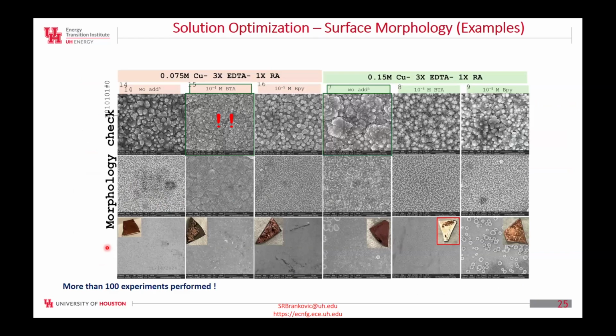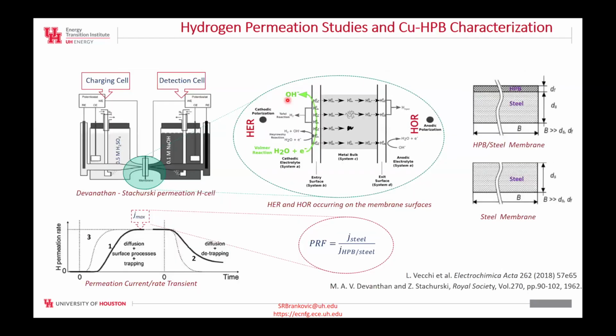So we have done a lot of work, especially this year, working and understanding the effects of different additives and reducing agents, complexing agents on the morphology of the copper coatings, crack formation or crack suppression. We have many more of these, but I just give you an idea what kind of a survey we have, from effects of the concentration of the copper in the solution to effect of complexing agents such as EDTA on the morphology of the copper coating. And we are really looking for the highest density coatings with no defects, no cracks, and these kind of things.